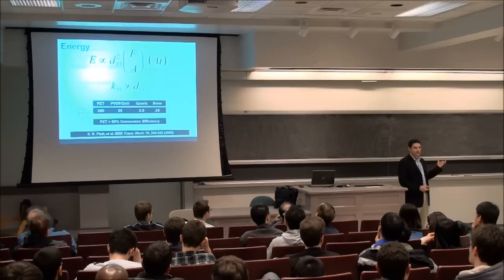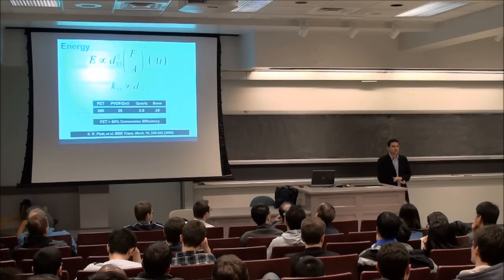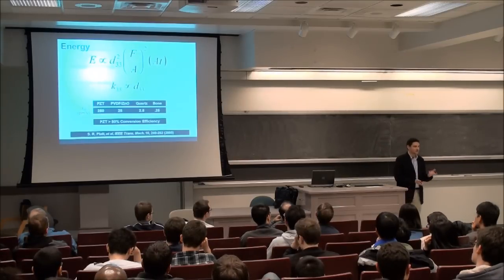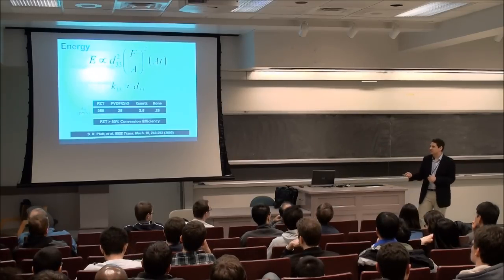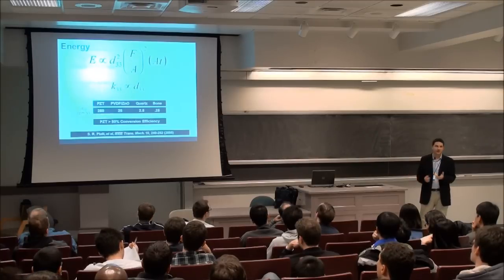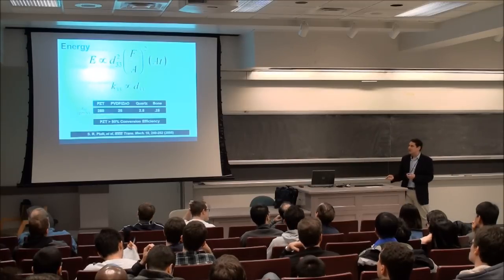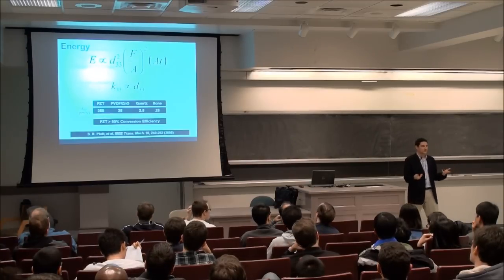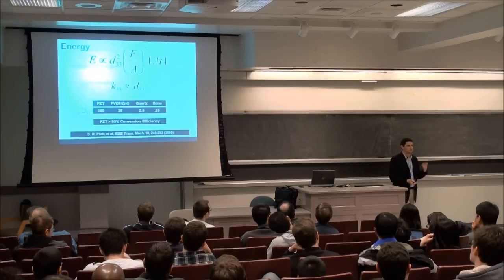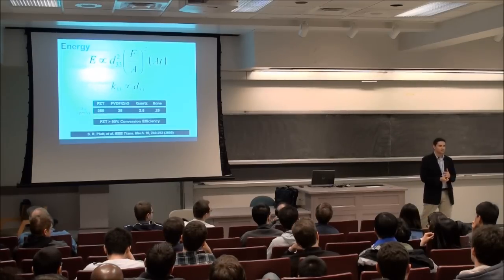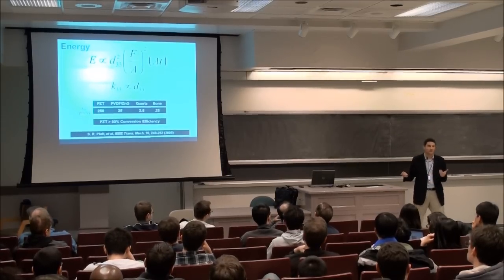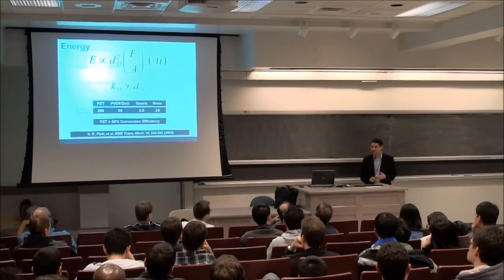Second thing is naturally occurring materials, quartz, which is piezoelectric too. The tetrahedron is actually a piezoelectric system. But again, it's a very weak coupling. The d value is quite low. PVDF is a polymer that's piezoelectric. And zinc oxide, you've heard a lot about zinc oxide. It's actually piezoelectric, but it's not any better than PVDF, it turns out.